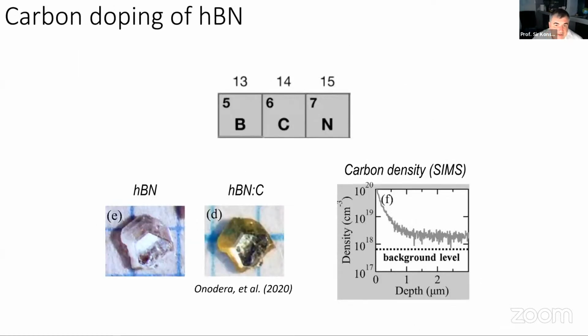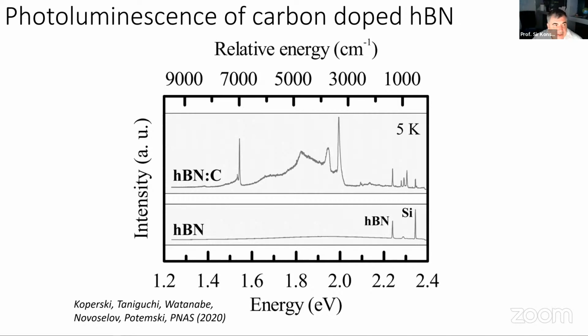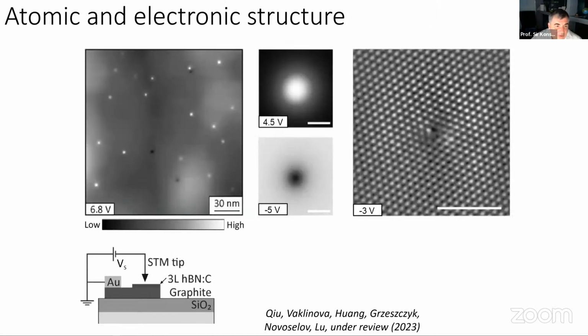So as I said, boron nitride is probably one of the most promising in this case because it has a huge band gap, and we do know that in order to produce single photon emitters there, we have to dope it with carbon. The problem is, okay, we know that it works, and we can see in the optical spectra those sharp lines which are associated with the single photon emitters. The problem is that we still don't know what emits, what kind of defects, what kind of quantum dots emit in those crystals. If we don't know what emits, it means that we cannot design them further, and we cannot introduce rational design. To this end, we cannot even see them in the STM measurements.